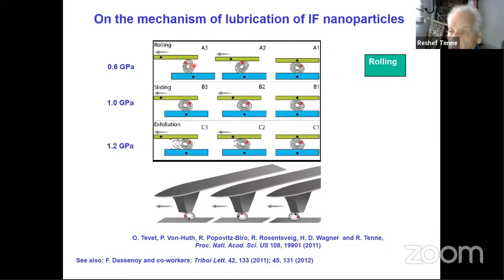Instead, they roll, and rolling friction is a mechanism that provides a very, very low friction coefficient. And you can go even to heavy loads of 0.6 gigapascal and 1 gigapascal, which amounts to actually 10 tons of load on your fingernail. You still get a very, very low friction coefficient. This has been beautifully shown by in situ microscopy, which I will not discuss further, by Ofer Tevet from my group and Fabrice Dassenoy from Lyon. And this demonstrates the usefulness of these nanoparticles as lubricant.